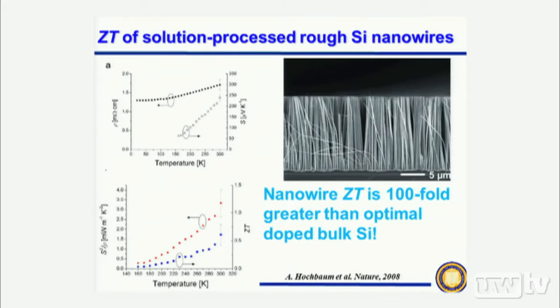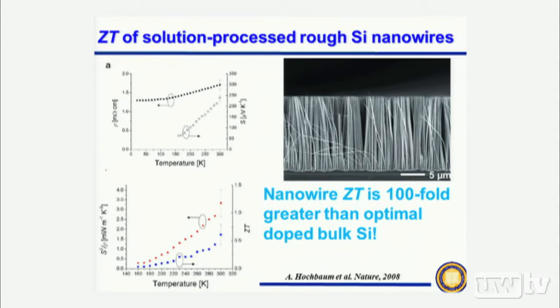Okay? And then after a couple of years of more efforts in terms of reducing the thermal conductivity, very recently we developed this very simple process. It's a solution process of making these wafer scale silicon nanowire array on, let's say, a 6-inch wafer. And the key feature here, as I said on this slide, is roughening of these silicon nanostructures.